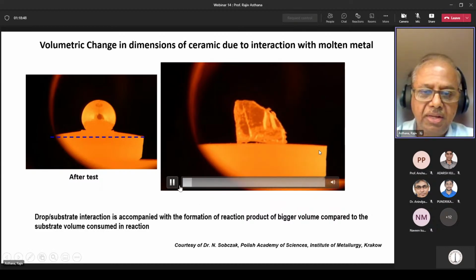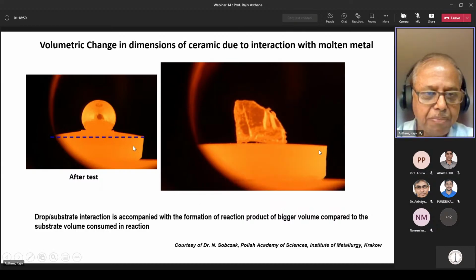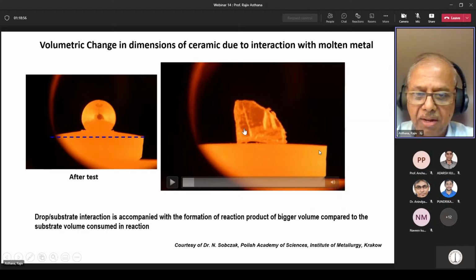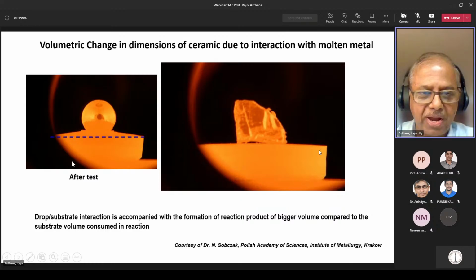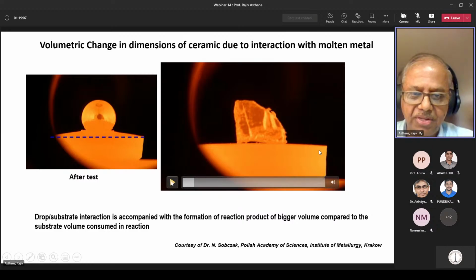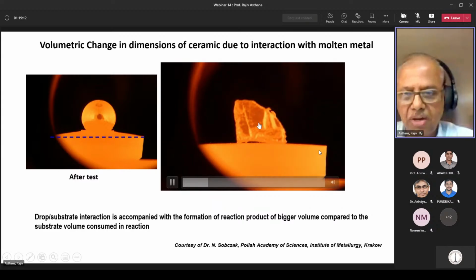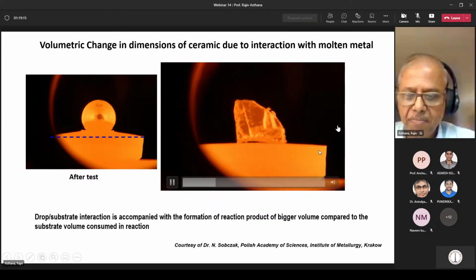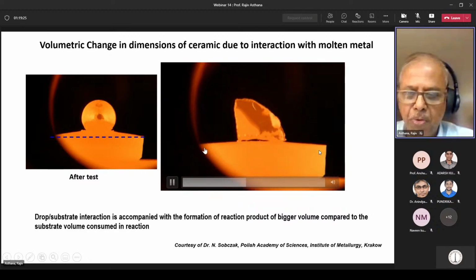There are changes in the surface of the substrate. So initially the substrate might be flat when it is in contact with the solid metal in the vacuum chamber, but as the reaction takes place, the volumetric changes from reaction will change the shape of the substrate. It becomes more convex. You can see here in this example, it is solid droplet or solid piece of metal that is going to melt. The surface is still more or less flat, but as the liquid forms and reacts with the surface of the substrate, you will see the surface becoming more and more convex.